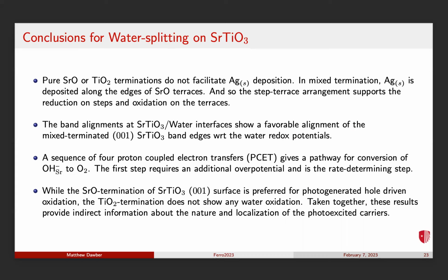And then the real clue as to why you need both surfaces is the process that we think is what allows this reaction to occur on the strontium oxide surface. So you really need the 2 things together, right? The titanium dioxide is vital because it puts your energy levels in the right place, but the strontium oxide is where the reaction is occurring. And they need to be in close proximity to each other.